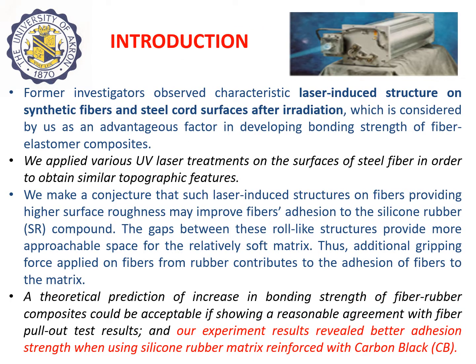Former investigators observed characteristic laser-induced structure on synthetic fibers and steel cord surfaces after irradiation. This is considered an advantageous factor in developing bonding strength of fiber-elastomer composites. Thus, we applied various UV laser treatments on the surfaces of steel fiber in order to obtain similar topographic features.